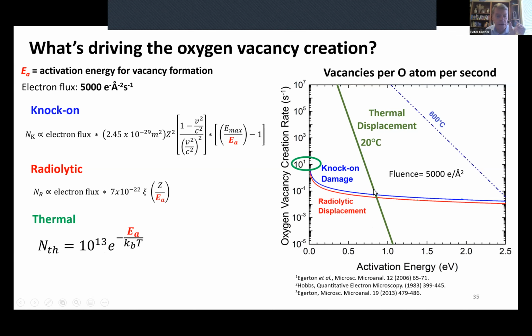The reason that's important for us is that we know the vacancy creation energy varies from one site on the surface to the other. So the most active sites are going to be associated with the smallest values of EA. And the other thing that this graph shows is if I heat the sample up to 600 degrees, all of the vacancy creation and annihilation, all of the dynamics in this case that we see, is completely dominated by thermal effects because of this Arrhenius dependence here.